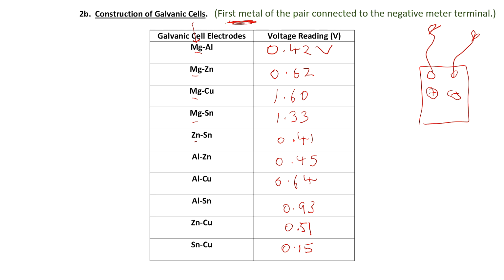These voltages that we obtained in this experiment are not exactly what one should obtain theoretically. There are actually theoretical values for these voltages, that are obtained by constructing these various galvanic cells. However, the fact that we constructed them very crudely, using a very crude salt bridge, and using electrodes and connections that may not have been perfectly clean of corrosion, so that the circuits were not exactly just through metal, but also through perhaps some resistive material. The results are not exactly what they should have been, but they give you an idea of how one can vary the metal combinations to produce different galvanic cell voltages, and this is exactly what happens in commercial batteries.